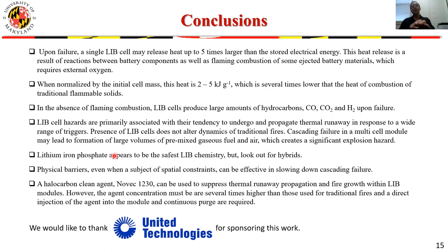Lithium iron phosphate is the best, the safest chemistry on the market. It does not have the energy density that is required for many applications, unfortunately. Also, there are some batteries on the market, according to anecdotal evidence, that claim to be high energy density lithium ion batteries. You probably want to stay away from those because those are usually hybrids. They contain mixed cathodes and can be as hazardous as LCOs.